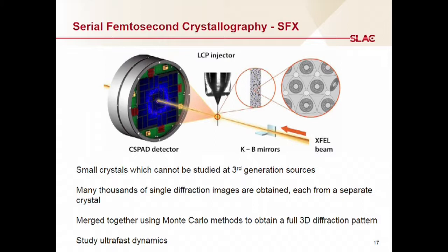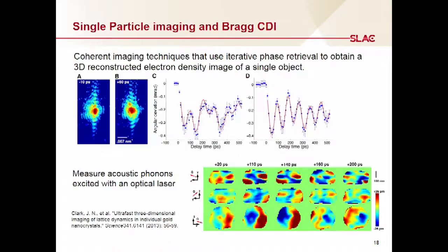Same thing with mixing. Let's say you have a protein crystal, and you mix some kind of substrate in to create some kind of reaction. The smaller the crystal, the more the substrate is able to penetrate into it, which means you have a higher percentage of excited states, which means you can get much better data than you can from a macro crystal. So this is where SFX really shines. And this is kind of where the future of protein crystallography is going at LCLS.